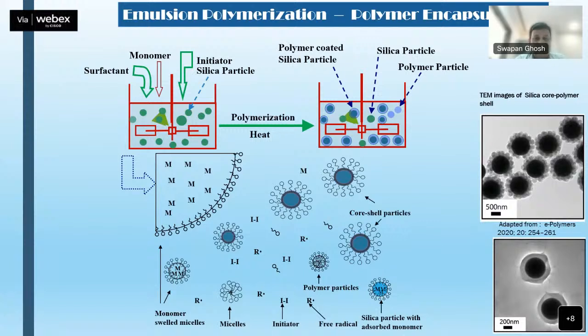They are hydrophobic in nature, and then it is stabilized by surfactant, which are dispersed in the system. When you start with that, there are many types of strategies that can be played around. For example, if I want that polymerization should take place on top of silicon oxide only, in that case I can do something. For example, I can think about a species which is already pre-adsorbed. For example, the silicon oxide surface is already pre-adsorbed by initiator, or maybe some surfactant I'll use where one part of that will act as a surfactant and the remaining part will act as an initiator.